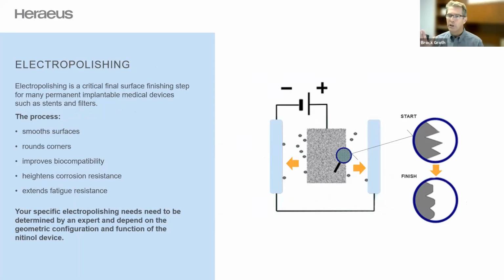What's happening is ions are flying off the surface, and they're flying off the surface in such a way that the sharp points shown on the magnified graphic there on the right, the start is very jaggedy, like the Rocky Mountains, and the finish is much more smooth, maybe like the Appalachian Mountains, or if you continue on, you'll get the plains of the Midwest. But what's happening is the ions are being removed, and it is smoothing the surface. The other thing that this material removal will cause to happen is things like a stent, when it's laser cut, you'll have these fairly square strut elements. More material will be removed from the corners, and you will round the corners.